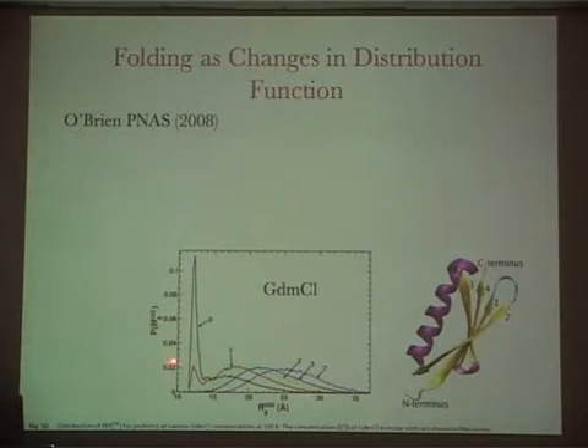Here, for example, is the distribution of radius of gyration. These are really calculated for this protein, which is protein L, by my former student, as a function of guanidinium concentration. Unfortunately, I won't tell you how to produce this because we introduced a very new method for actually computing these quantities. This is 7 molar guanidinium chloride, and you see only the large RG values are populated, whereas if you go to 0, it peaks around about 12 angstroms or so, and that's the radius of gyration that you'll calculate if you take the PDB structure for this protein L.